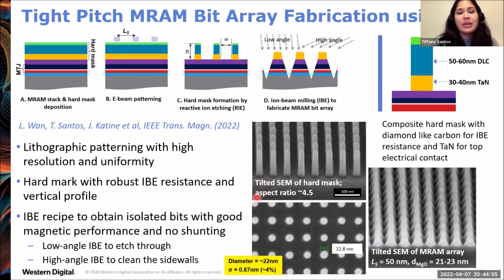This is the tilted SEM and the top-down SEM view of the hard mask. So very tall pillars of high aspect ratio hard mask with vertical sidewalls. So this is a good hard mask for then etching the MRAM bits. And that is done by ion beam milling, first at a low angle to etch into the depth of the metallic multi-layer to form the bits, and then again a next step at high angle to mill away the redeposited material on the sidewalls and prevent electrical shunting.